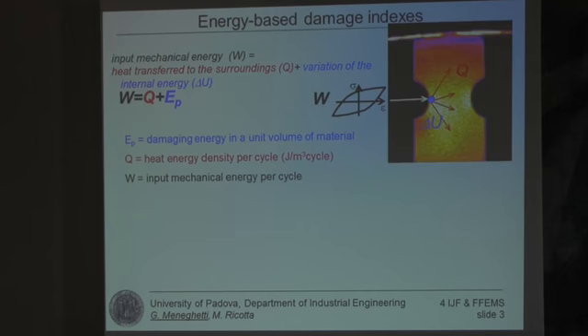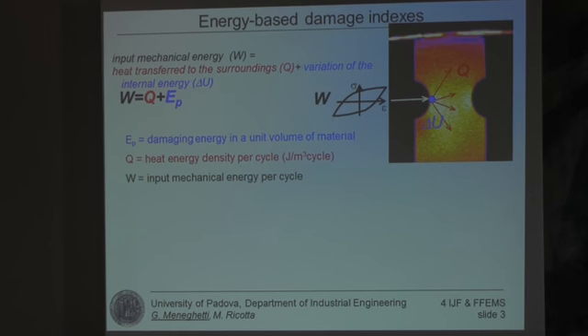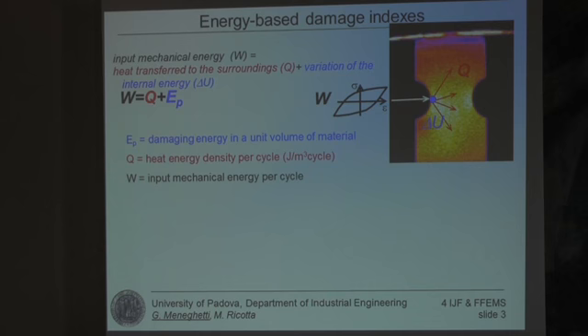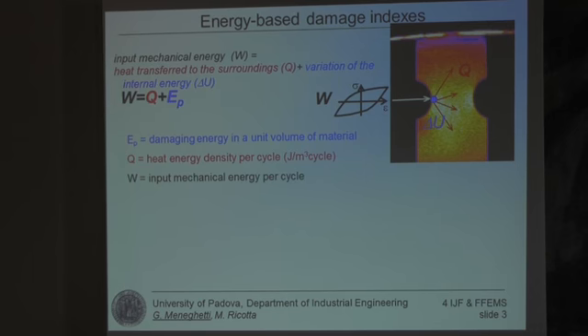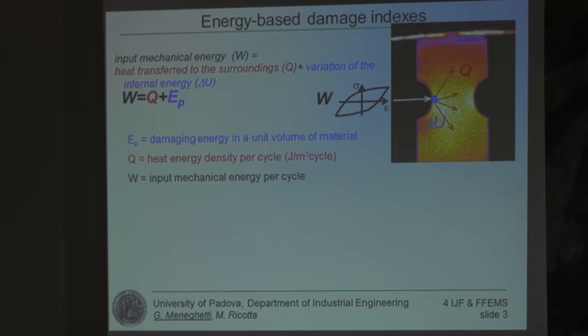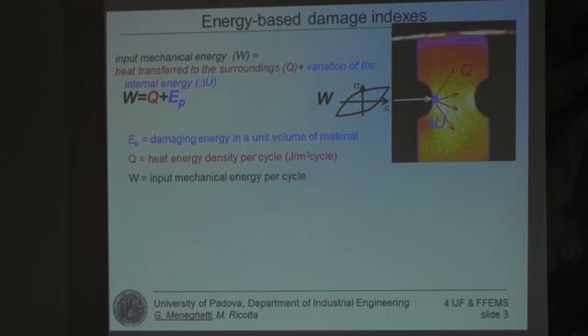So, first of all, we know from the literature, many researchers wrote the energy balance at a point of a material subjected to fatigue loadings. We know that we have to spend some mechanical energy to input into the material to induce crack initiation and then propagation. Such energy splits into two. Some energy is stored inside the material and it is responsible for damage accumulation leading to initiation and then propagation of the crack. But some of this energy is dissipated as heat. As a first point, of course, looking at the energy balance, our attention is kept by these energy terms because this energy term is the one responsible for fatigue damage accumulation. But I will show in a while that this is quite difficult to measure, at least in a simple way.